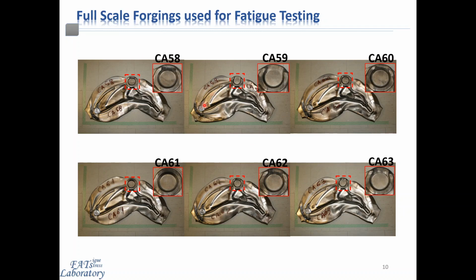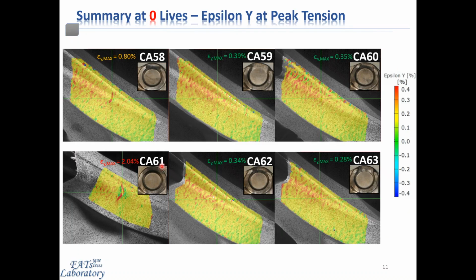These variations caused by very slight differences in the material flow, alignment of the initial billet within each of the forging processes, and the process control itself, etc., can sometimes result in defects which can be very detrimental to fatigue. Thus, analyzing them and quantifying their effect can be of great importance to develop the forging process to allow for components which will be robust under fatigue loading and be much more predictable in nature.